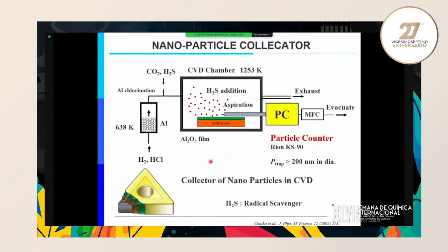Actually, in these studies, since alpha alumina, for example, is a very important material for cutting tools, nanoparticle formation in the gas phase was studied. This is actually my former student. And in industry, alpha alumina is prepared from aluminum chloride, CO2 as the source gas, and hydrogen gas. Usually in the CVD of alumina, nanoparticle formation is very significant, and we can count the nanoparticles by using a particle counter. By using a particle counter, we can estimate how much nanoparticle forms.